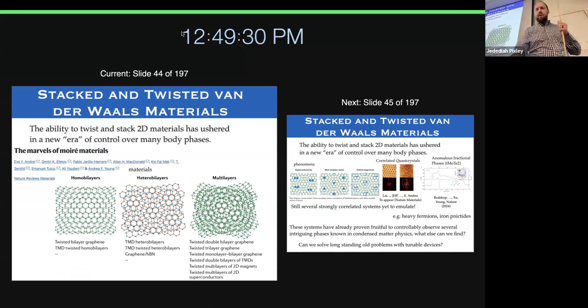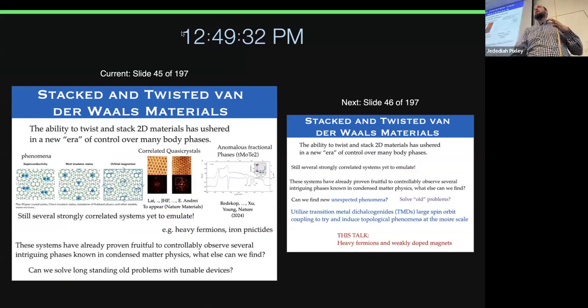And what we've gotten from this is an amazing range of phenomena. From my perspective, as a graduate student in condensed matter physics, a lot of the phases that we're seeing in experiment now were theorist dreams 15 years ago. It's really amazing to see where the field has come. So we regularly see superconductivity reproduced. There are Mott insulating states, or also symmetry-broken insulating states. We have very clear orbital magnets with quantized responses. This is made purely out of carbon. It's pretty amazing: an orbital magnet purely out of carbon. You can also make strongly correlated quasicrystals. It will be appearing in Nature Materials in a month.